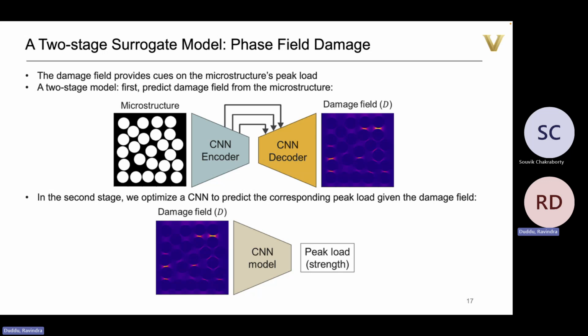Okay, so first you go from image to image, and then you use the damage image through that VGG16, and then you try to make the prediction for peak load. So instead of doing it in one step with the baseline, now you're doing a two-step. Okay, how does this do?